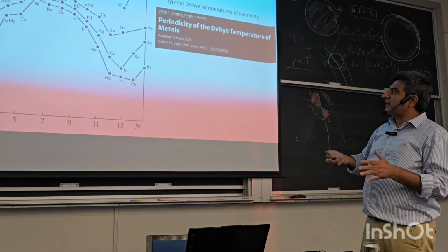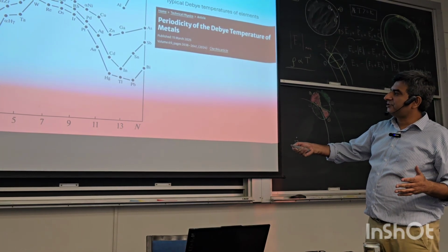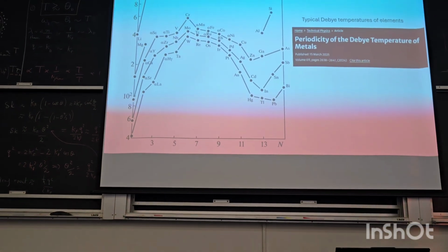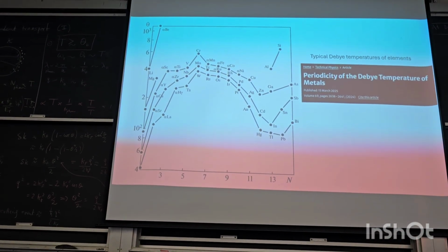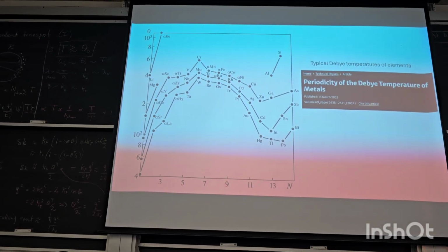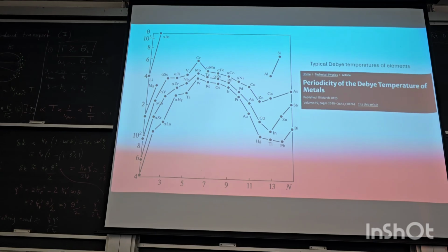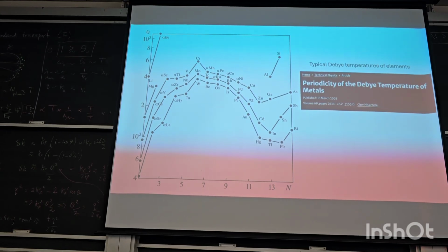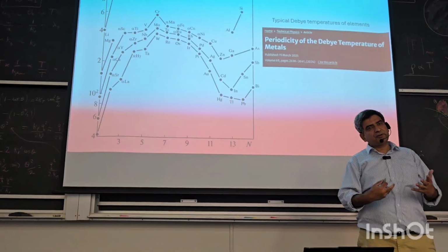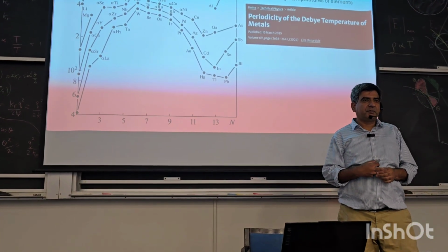So all of these Debye temperatures are inside this regime of between 100 and 700 or 800 kelvins. Okay? And this Debye temperature is a characteristic of the solid. It's empirically determined. So you do a heat capacity versus temperature plot, and from a fit of that plot you determine the Debye temperature.